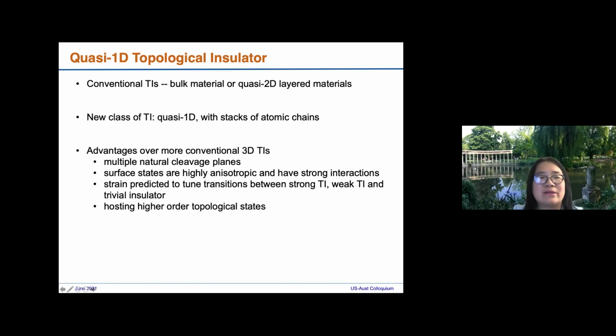Conventionally, topological insulators are either bulk materials or quasi 2D layered materials. These quasi 1D materials basically have stacks of atomic chains, so you have some advantages over the more conventional 3D TIs. For example, you can have multiple cleavage planes, because we can cleave along the chains, and it's also layered. Surface states are highly anisotropic and have strong interactions. There are predictions to tune the transition between strong TI, weak TI, and trivial insulators by using strain, and they are also predicted to host higher order topological states.